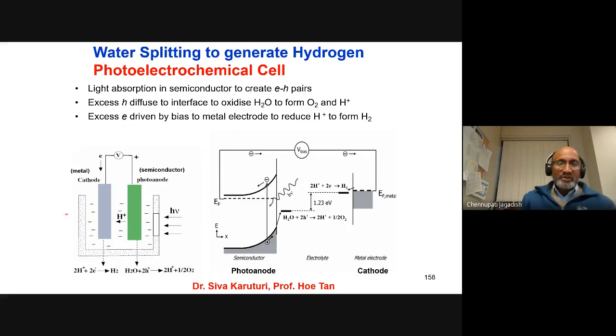and other things. In this case, essentially you take a cathode, which could be a metal like platinum, and a photoanode, which is a semiconductor, and you shine light on top of this photoanode, generating photocarriers, electron-hole pairs. The holes go and oxidize water to create oxygen and protons, and the electrons go to this side and interact with the protons, reducing protons to make hydrogen. For this reaction to work, the energy you need is at least 1.23 electron volts, but generally there are also some losses in the system, so typically you need about 1.6 electron volts or so to make this work.